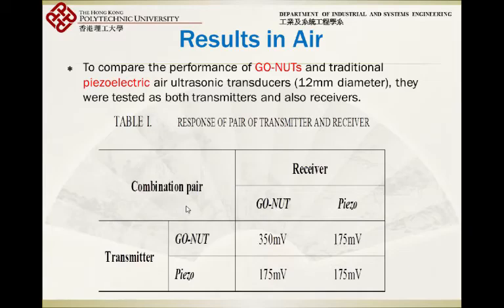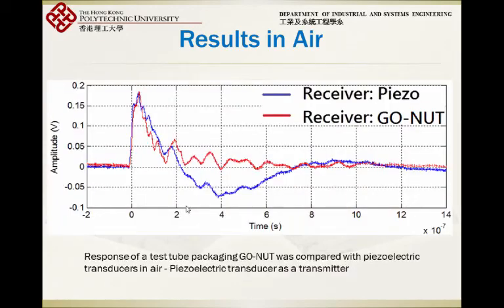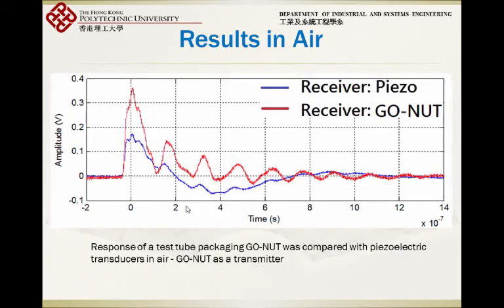So this is the result. At first, we try to compare with the ultrasonic transducer made by piezoelectric transducers, and you can see for the receiving for the piezoelectric transducers, this is the signal of the piezo, and then this is the signal of the GO-NUTs. So you can see their amplitude is comparable, about 0.15 volts. So the input is only 4 volts, and we can get 0.15 volts. So it can be considered, I would say, pretty efficient.